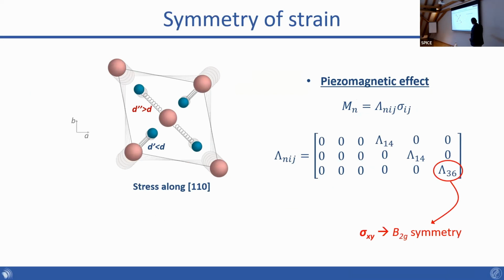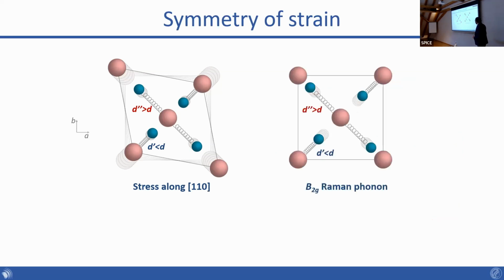The element that we're most interested in is this one, 3,6, which tells you that you get a C-axis magnetization when you apply an in-plane XY strain. And this particular term has B2G symmetry with respect to the lattice, okay? So what we can do is look to see what kind of modes we have in this material and see if we have something similar. And in fact, there is a B2G Raman mode in this material.